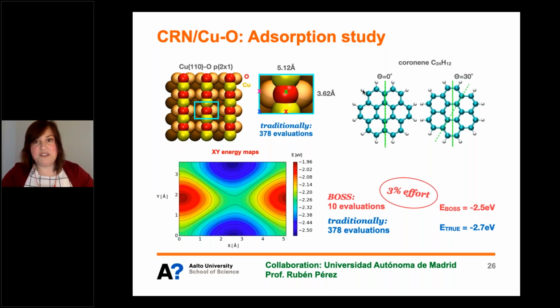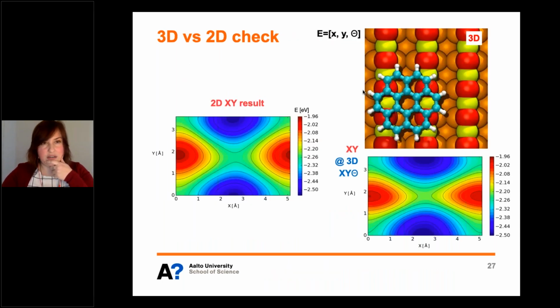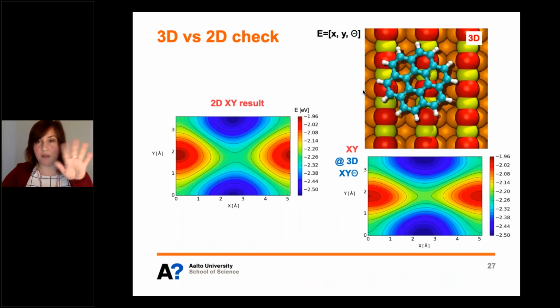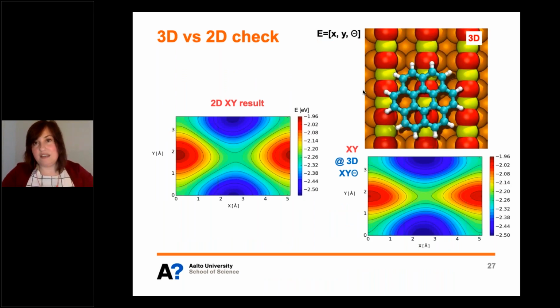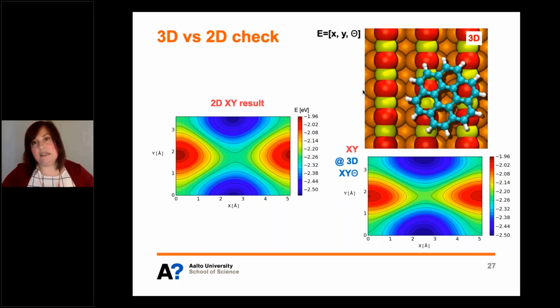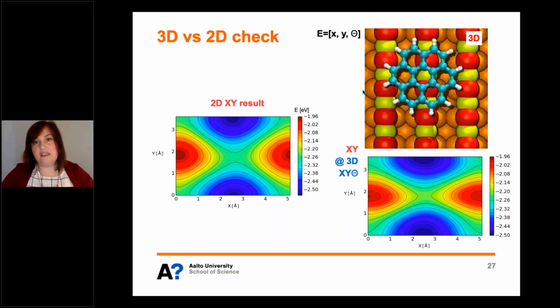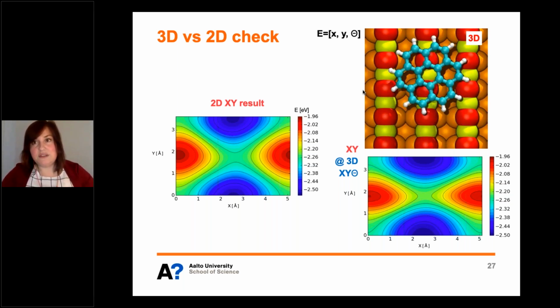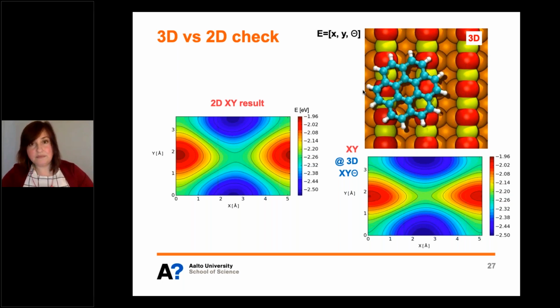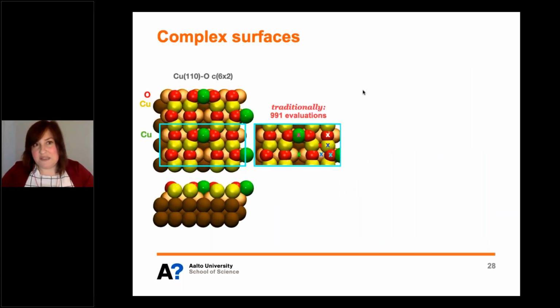I mean, 3% is very good, but this was still a 2D simulation, and we wanted to check the full 3D case with the molecule rotating in plane. So this allowed us to build a 3D surrogate model, and then we cut it again in the XY plane, and indeed, this was the solution. Thank you, BOSS. Now, this was a very simple surface.